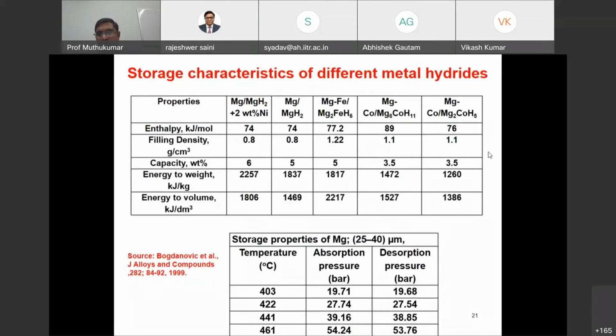Again, some more basic information here. For example, when you are absorbing the hydrogen, if you supply the hydrogen at high pressure, say about, you see this particular alloy, pure magnesium, and if you supply the hydrogen at about 50 bar pressure, then you can get the heat output in the range of about 460 degrees Celsius. Okay, 460 degrees Celsius. So by manipulating the supply pressure range, you can get the heat output at a higher temperature as well.